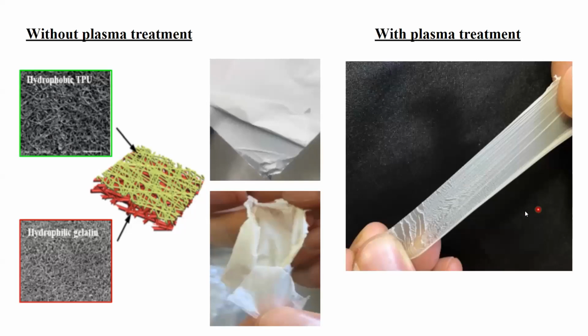Without plasma treatment, we face some adhesion problems since TPU is hydrophobic and gelatin is hydrophilic. From these two pictures, separated layers can be seen clearly. For that reason, plasma treatment was used as a surface activation technique to provide better adhesion between the layers. And apparently, adhesion of two layers was achieved successfully with plasma treatment, as we can see at the last picture.